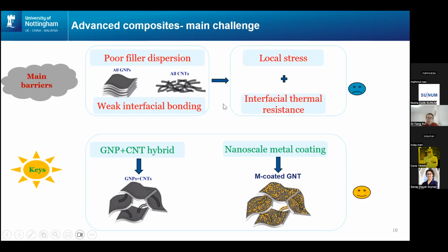To solve this problem, we propose to find a more effective dispersion strategy. From theoretic study by other researchers, we found that if graphene and carbon nanotubes mix together, they will work as effective spacers to separate them. So we propose to combine graphene and carbon nanotube together.